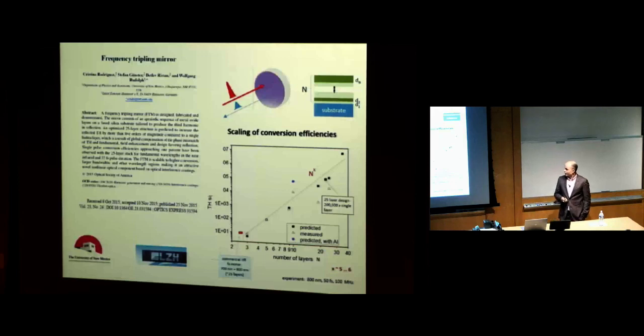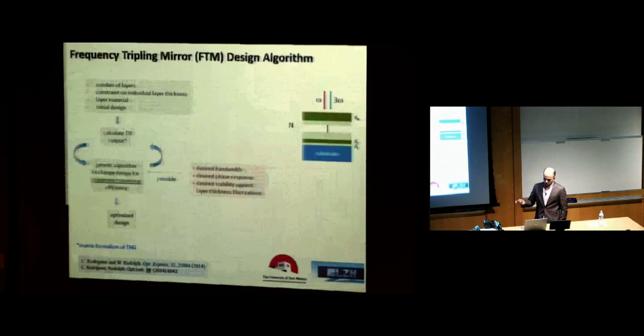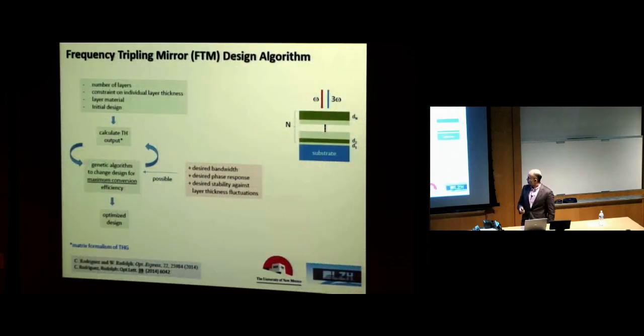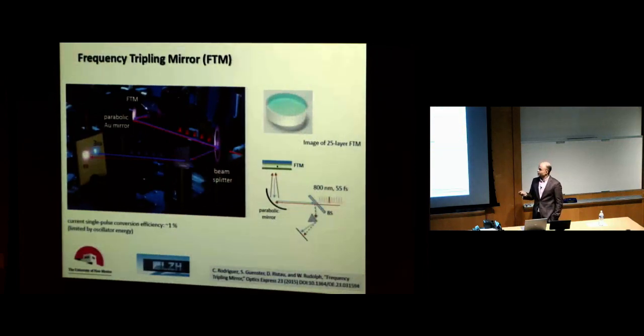Regarding nonlinearity, there is a group of Wolfgang Rudolph from the University of New Mexico, together with people from Laser Centrum Hannover in Germany. They produced a special design for a multilayer coating and generate the third harmonic. They made a design in such a way that the mirrors themselves generate the third harmonic with very high efficiency, I think now about a few percent. For some applications, it might be very interesting because the mirror is very thin, and the light going through the multilayer structure doesn't experience much nonlinearity. For this particular case, it can be used at much higher intensity, because if you use some crystal, you're limited in intensity.